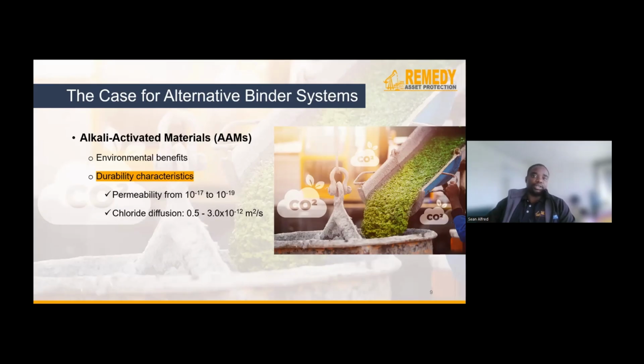As a side note, although I didn't dive so much into them, when you look at calcium sulfoaluminate cement, these derive their strength from the formation of ettringite, which is like needle crystal formations, and those offer a more conservative alternative with performance comparable to OPC systems for permeability and enhanced chloride resistance due to the ettringite formation and moderate carbonation resistance. So they're not as powerful as the benefits that you would get from AAMs.